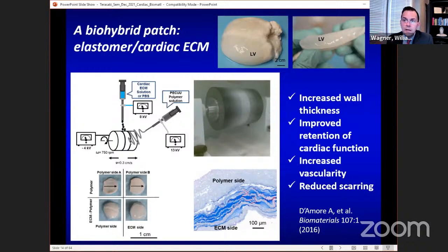And by controlling the speed of the drum, we could even make it anisotropic and put it in the heart in different orientations. I'm not going to go into the orientation stuff. I'm just going to focus on the patch. So what we did is we made what we call an open face sandwich. Initially, we did polymer with little to no ECM to make like a sandwich bread type side. And then we cranked up the ECM, which you see in blue here, to make a lower layer that was rich in jelly, kind of like peanut butter and jelly.